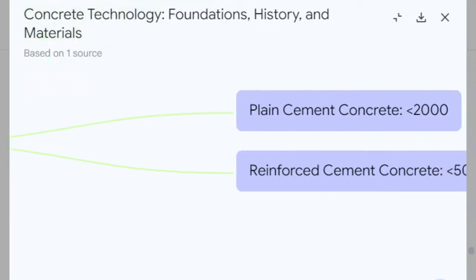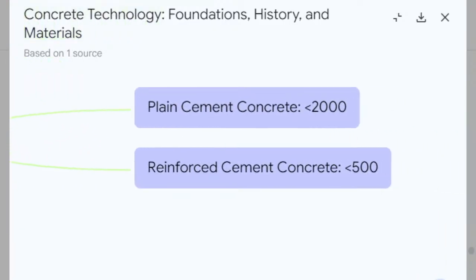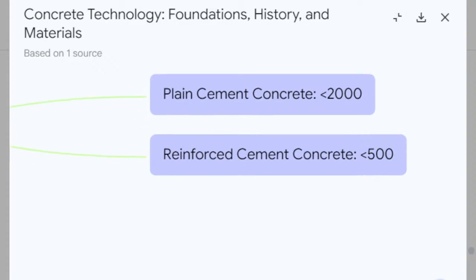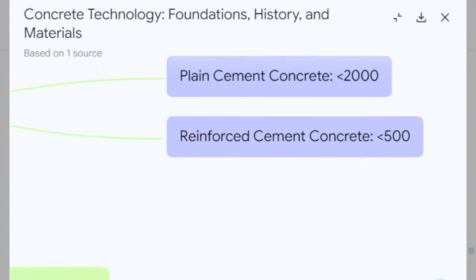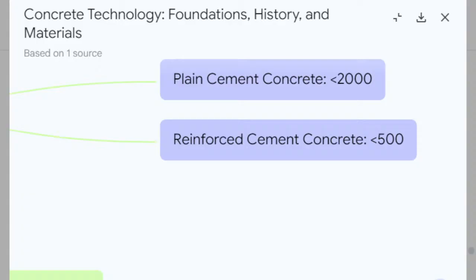Chlorides. This is the big one, especially for RCC. For plain concrete without steel, PCC, you might tolerate higher levels, maybe up to 2,000 mg/L. But for RCC, where steel rebar is present, the limit drops drastically, often to just 500 mg/L, and sometimes even lower for really critical structures like prestressed concrete. Why such a huge difference for reinforced concrete? Because chlorides are the arch nemesis of steel reinforcement. They break down the protective passive layer that normally forms on steel in concrete's alkaline environment, allowing corrosion or rusting to start much more easily, even if oxygen and moisture levels are relatively low.